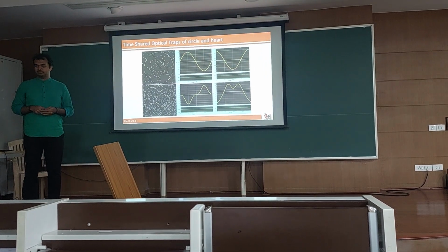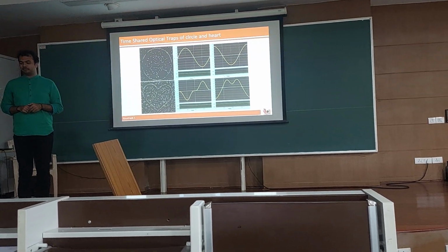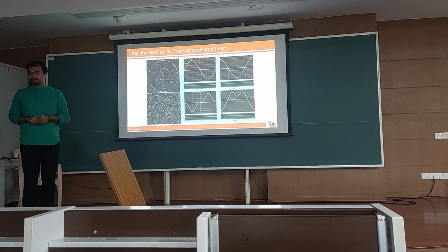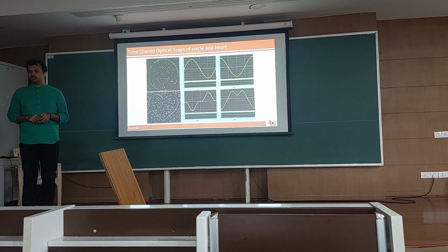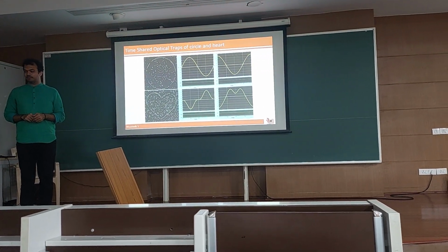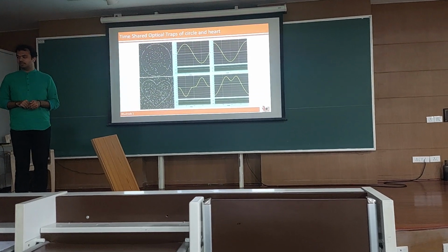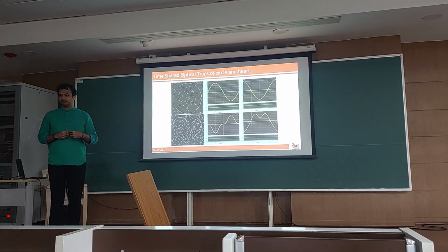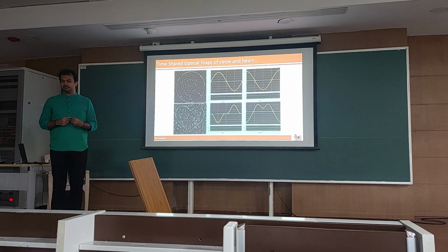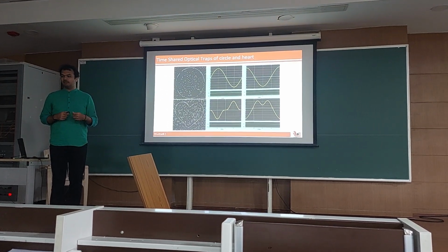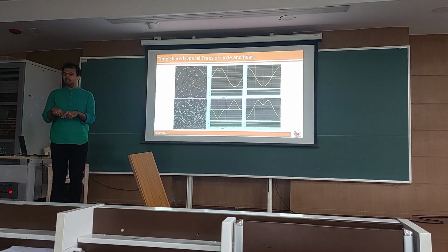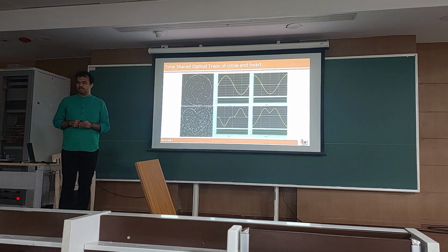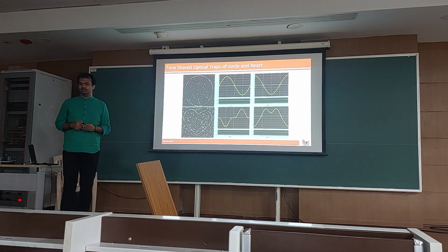Here is one question about phonons. In normal solids, because of charges, you have optical and acoustic phonons. But here you can have only acoustic phonons. That is true. Can you simulate something where we can have two charged spheres? We can do scattering also, but I don't think we can completely mix the two types of spheres with different charges. We have to make sure of the stability of the colloid, otherwise it will coagulate. So they will form domains of two charges and so on. So that will be non-trivial.